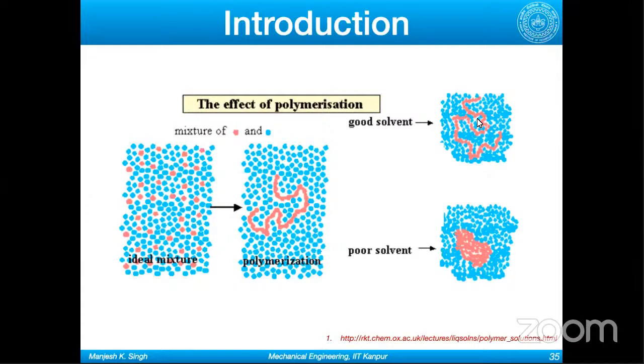But when you have a poor solvent, that means the polymer doesn't like the solvent, or you can say hates it, or maybe hate is too strong a word, so it will avoid any contact with the solvent as much as possible. It will collapse in the form of a sphere or a globule to minimize its contact with the solvent. So whenever you say a poor solvent, you'll basically see the polymers collapse. And physically, if you want to check whether a solvent is a good solvent or a bad solvent for a polymer, you just add the polymer to the solvent. If the mixture is still transparent, that means it's a good solvent, because the polymer is happily opened up.